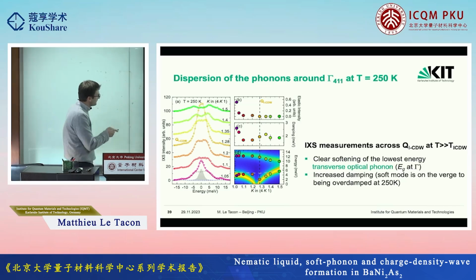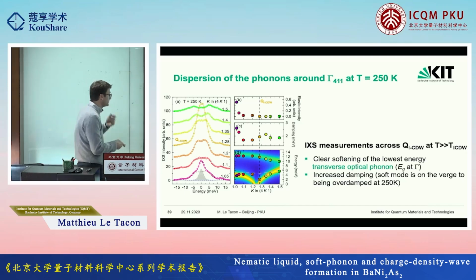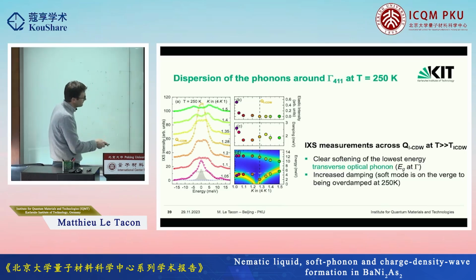And it can be somewhat complicated to fit. So you have these damped harmonic oscillators. You have to take into account the resolution effect. And you have this elastic line, which is also increasing, but somewhat hard to get exactly the thing. But it just turns out you can just fit this profile with the phonons.